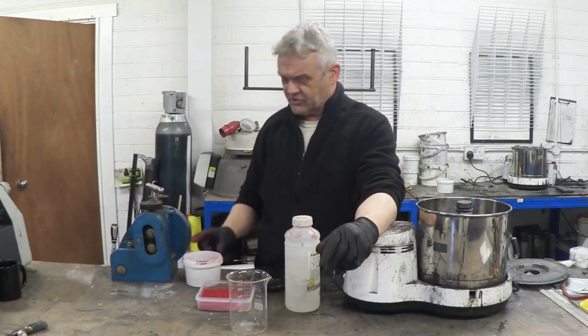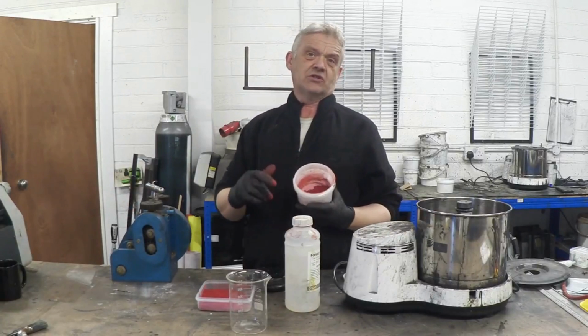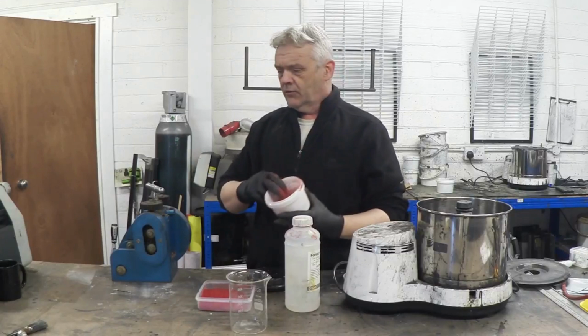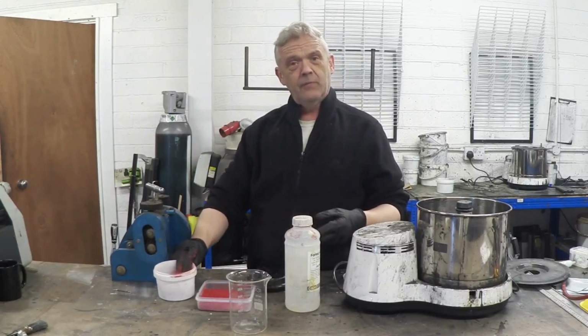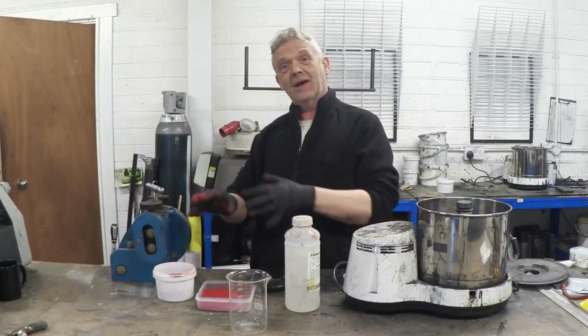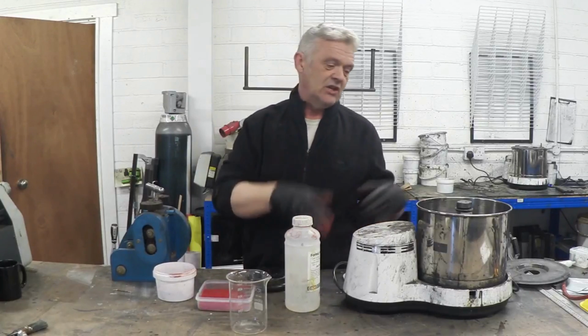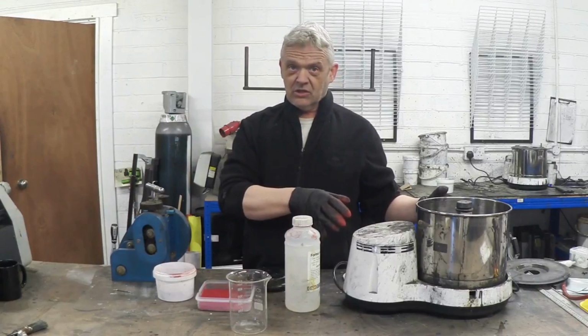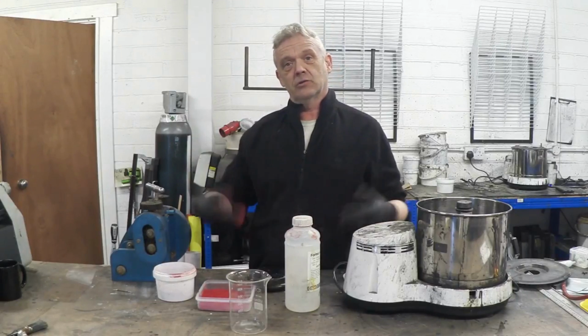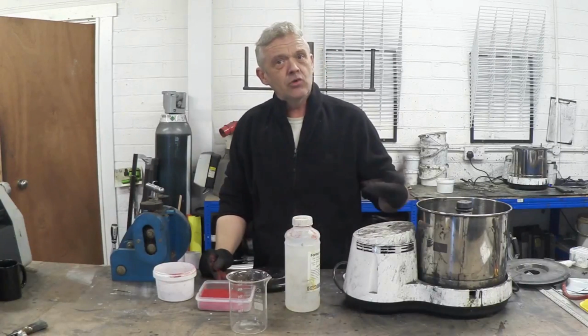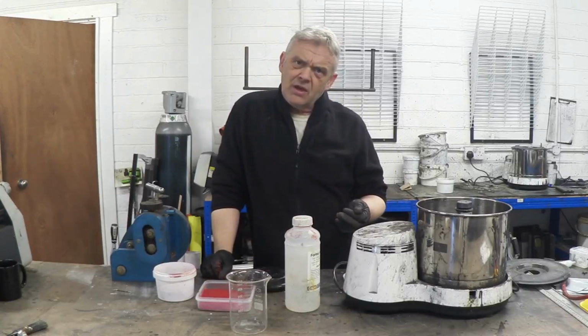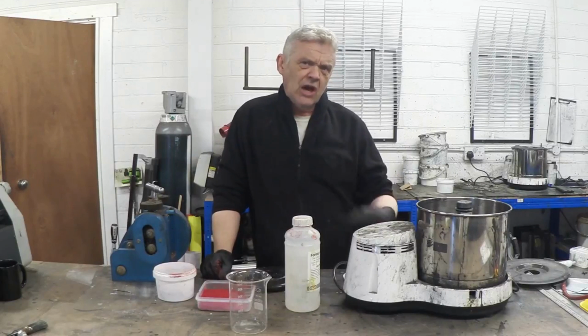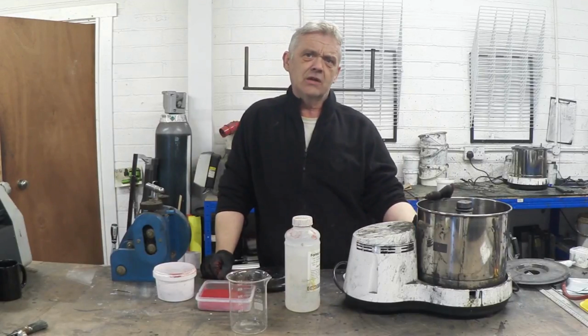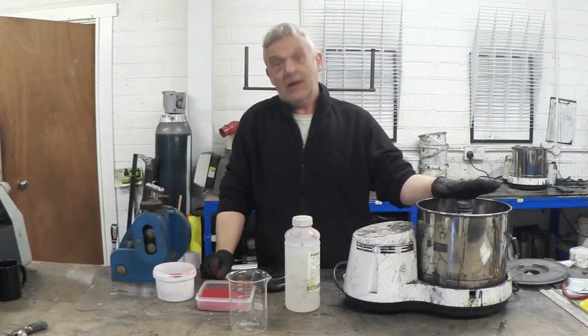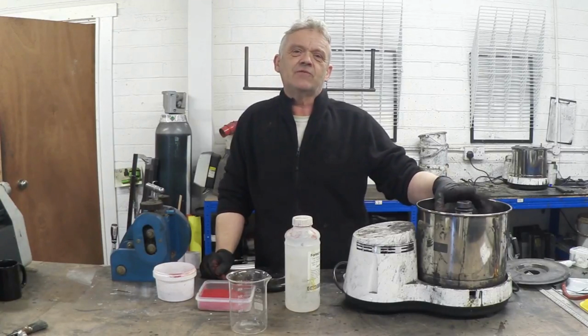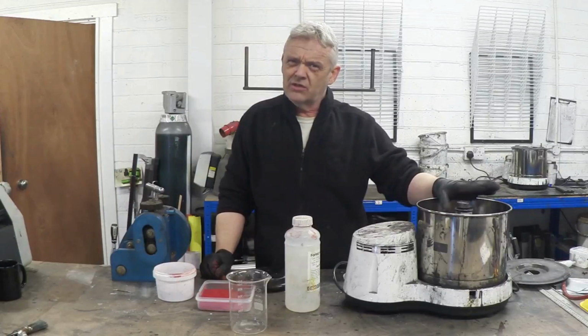Now we're going to use copper oxide in there, and we're going to use copper 1 oxide, which is this red copper oxide. The copper 2 oxide is the black stuff, this red stuff is the copper 1 oxide, and that will reduce with the formic acid under mechanochemical synthesis conditions into copper nanoparticles and copper formate, and it's a bright blue colour. Now, common to all mechanochemical synthesis, it takes quite a long time, so it's about a day or two grinding away in here. So I'm going to put this away in the fume cupboard and leave it for a day or two, just occasionally checking on it to have a look.